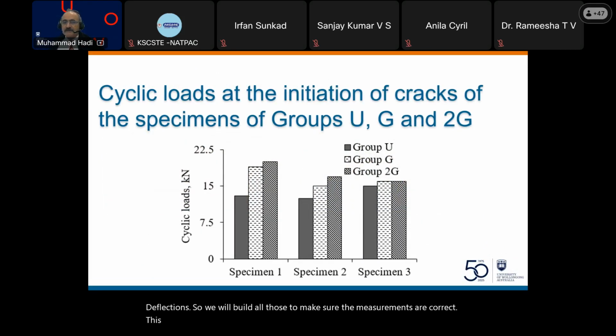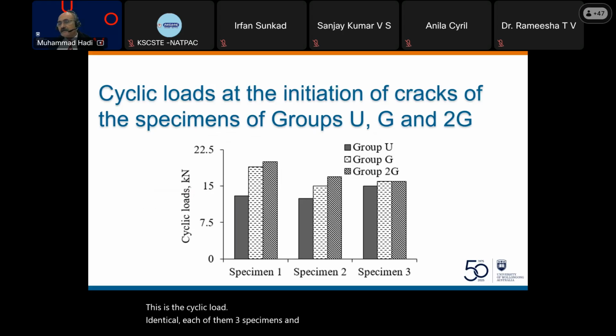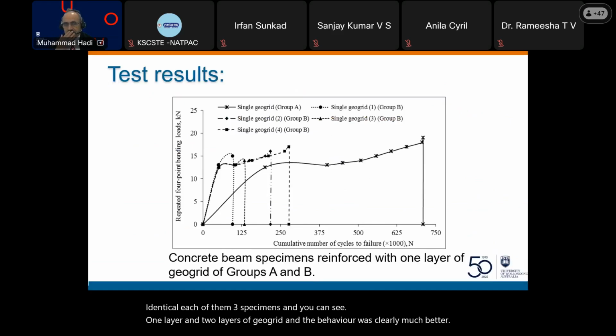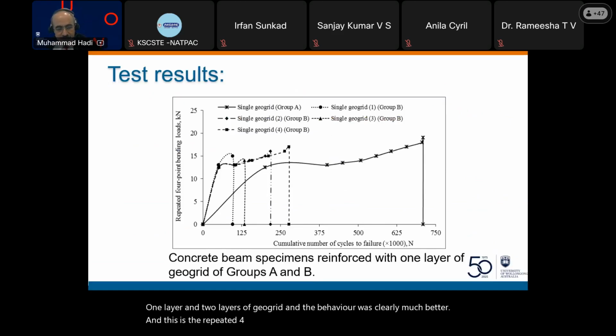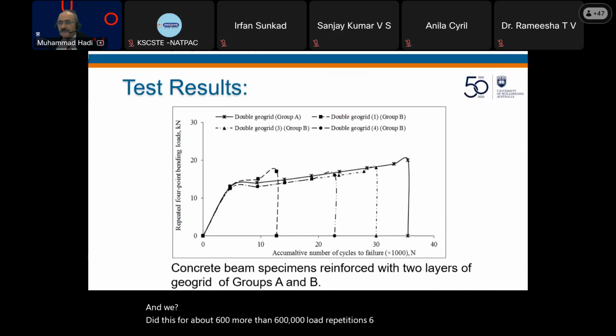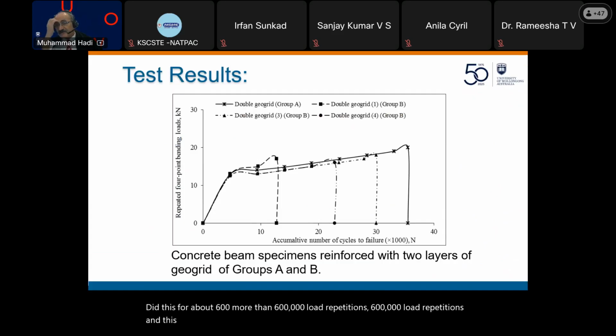This is the cyclic load, identical, each of them 3 specimens, and you can see 1 layer and 2 layers of geogrid, and the behavior was clearly much better. And this is the repeated 4-point bending, and we did this for more than 600,000 load repetitions. And this is the cumulative number of cycles where the load applied and failure occurred.